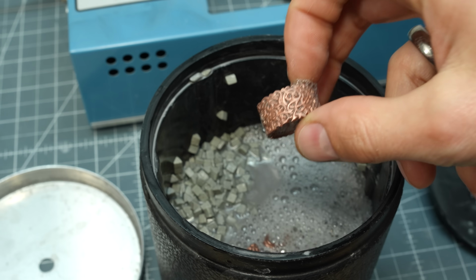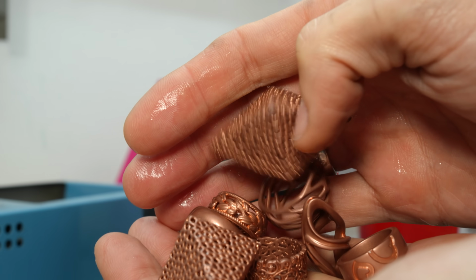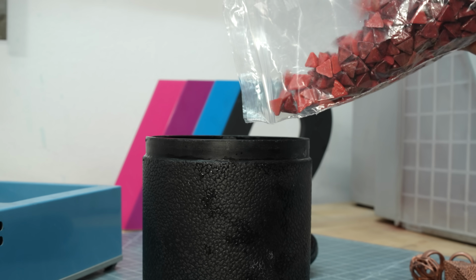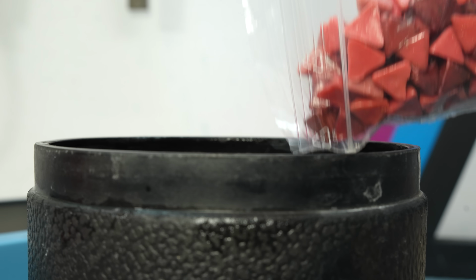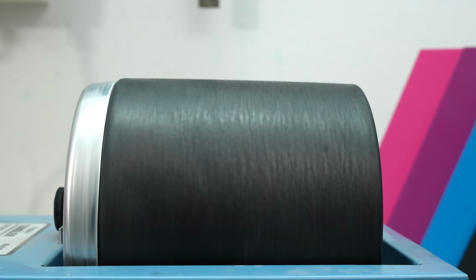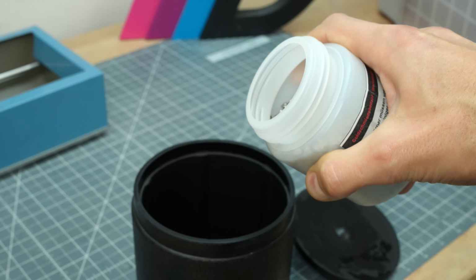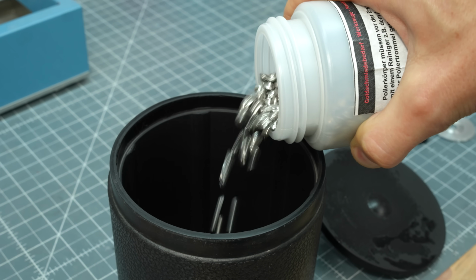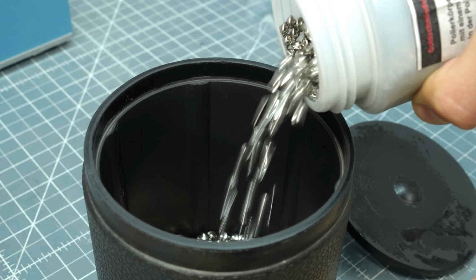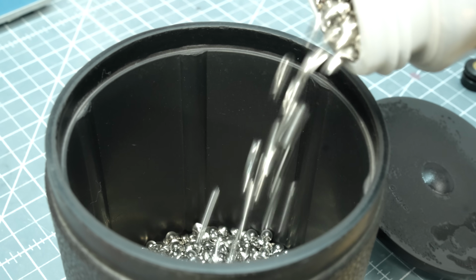It feels like it's getting worse and worse. Now plastic polishing tetrahedrons with fine polishing compound. You know the drill, always clean the container thoroughly. 6 hours. Finally, time for pre-polishing. For this, I use stainless steel satellites with a drop of dish soap and water. 6 hours.